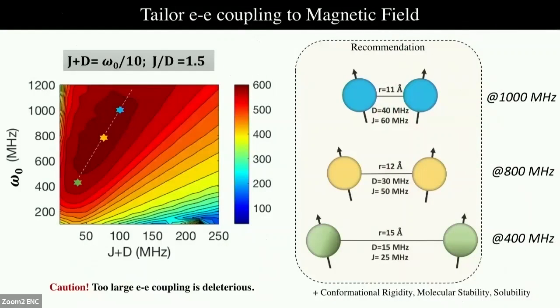With this understanding of what the coupling between two electrons should be for cross-effect DNP, we have a recommendation for improving DNP at higher magnetic field. The recommendation is that we need to tailor our electron-electron coupling to the external magnetic field. For example, if we are doing DNP at 400 megahertz, the coupling should be weaker. It should be roughly 1/10 of the Larmor frequency. So the net coupling should be roughly 40 megahertz. And out of that, 5/8 of the contribution should come from J coupling.